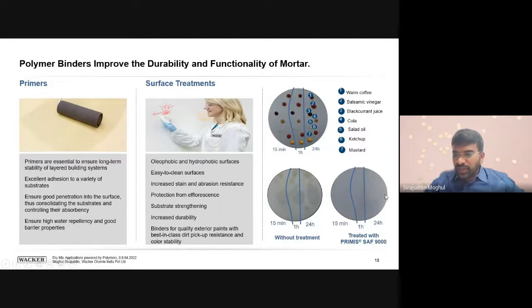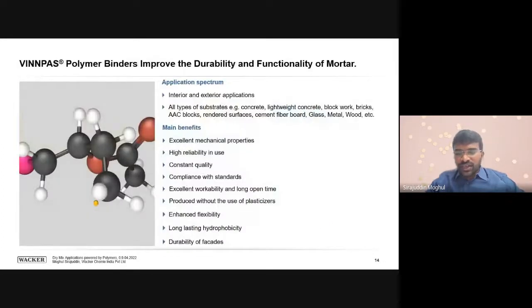If it is a treated wall, and the treatment is just simple, you have to take polymer, add water to it, and just apply it on the surface. When you treat it with polymer, you will not get stains even after 24 hours. You pour something onto this wall or the floor, and then you clean it after 24 hours, and you will be able to clean it very easily. So these are some of the applications where we use polymers.